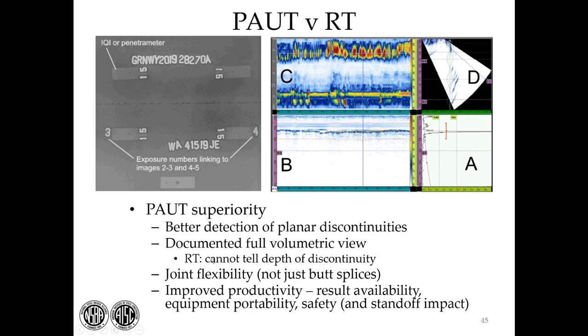And I'll emphasize again, with RT, you can't tell the depth of a discontinuity. With phased array, you can, as with UT. Also, RT is only useful for butt splices. Phased array and UT can also be used for T and corner joints, and phased array offers much better productivity. The results are available immediately as you scan. It's much safer. You don't have to worry about radiation in your shop or standoff. If you want to be safe with RT, you may have to either shoot at night or push workers away while you're working. You don't have to worry about that with phased array.